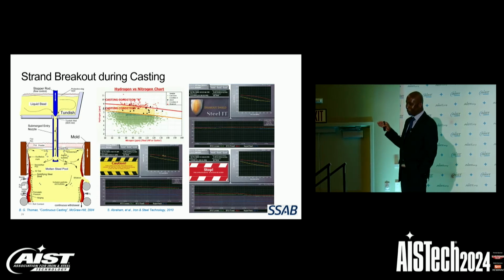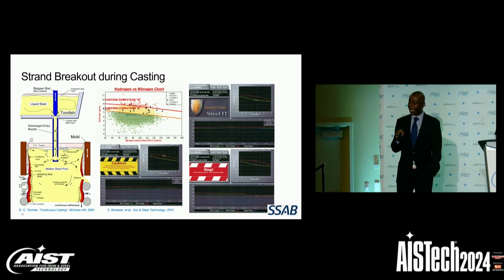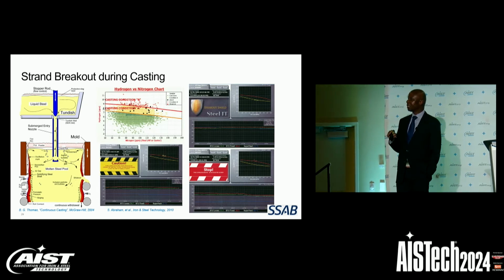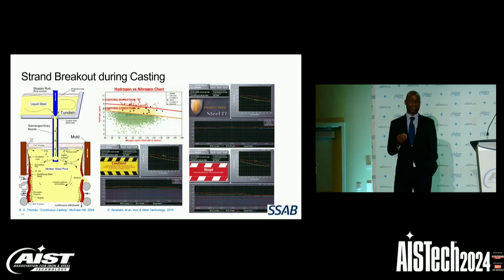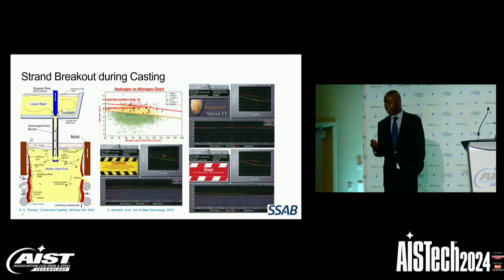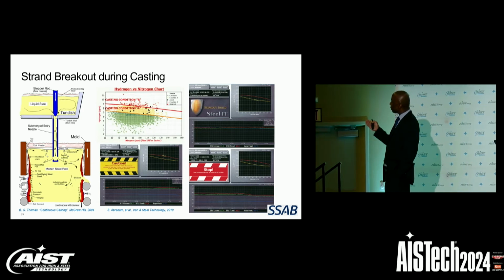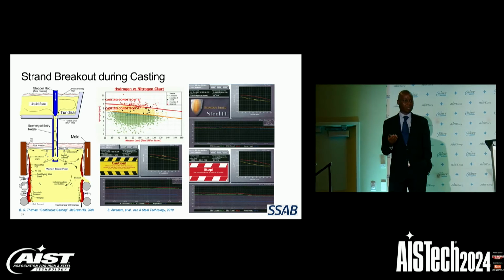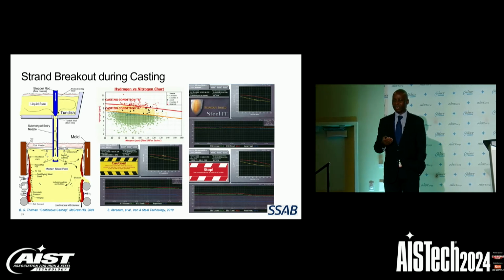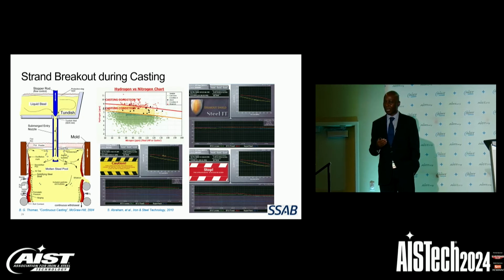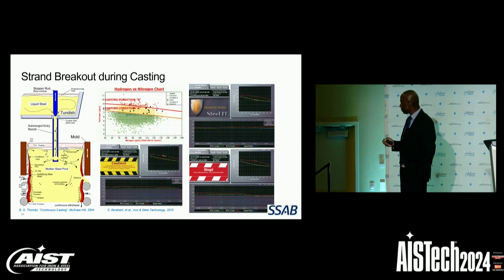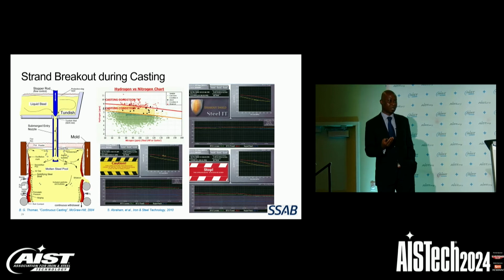So at the exit of the mold, the shell can be so thin that it cannot withstand the ferrostatic pressure of the liquid inside it. So this creates potential for breakout. So by looking at historical data on hydrogen-related breakouts, we found that with every 1 ppm increase in hydrogen, you have to decrease the nitrogen by 20 ppm to avoid the potential for breakout. We also understood the relationship between the hydrogen and nitrogen content of the steel and heat transfer during casting.